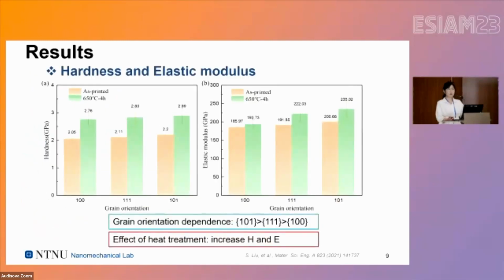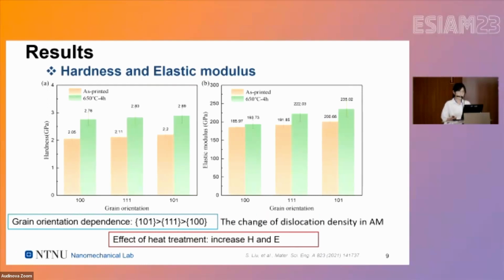So let's have a look at our results. For the hardness and elastic modulus results, we found that there is a grain orientation dependence on both the hardness and modulus, and the tendency for these two properties is the same. That is, grain 101 has the highest hardness and modulus, followed by 111, and then 100. The possible reason might be the change of the dislocation density during the AM process.